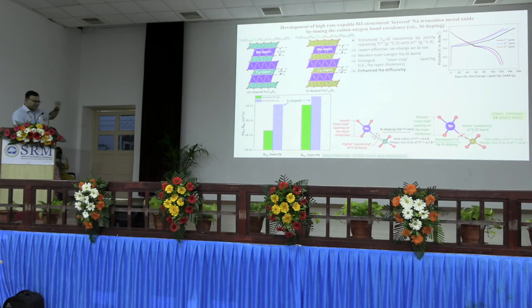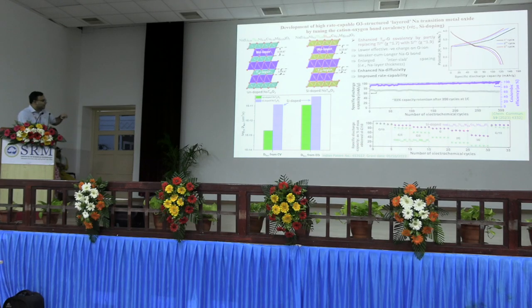Now this is another example. I don't have time to elaborate on this, but we can show that the same concept can be used to improve the rate capability. Normally the O3 structured layered transition metal oxides are not as rate capable as the P2, but even the O3 one can improve the rate capability by tuning the charge to size ratio and increasing the sodium interslab spacing. So that one can do.